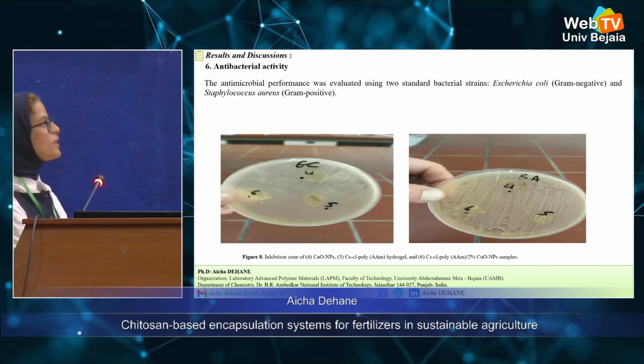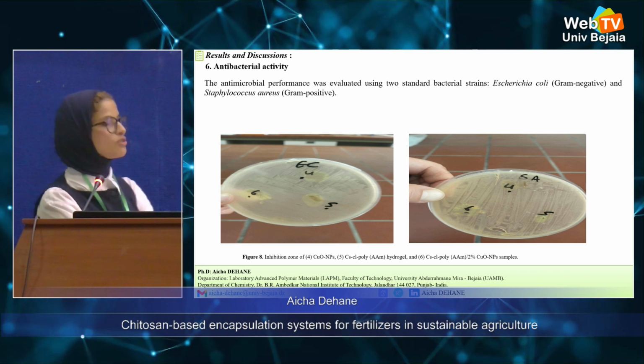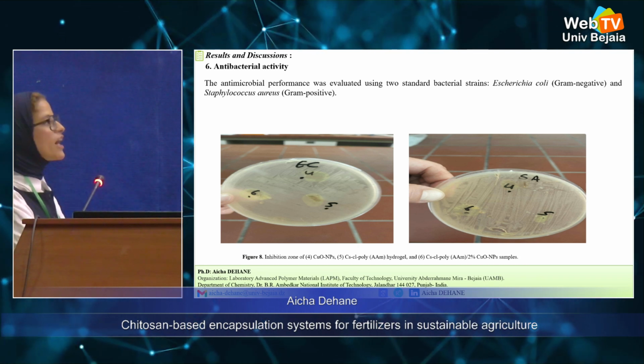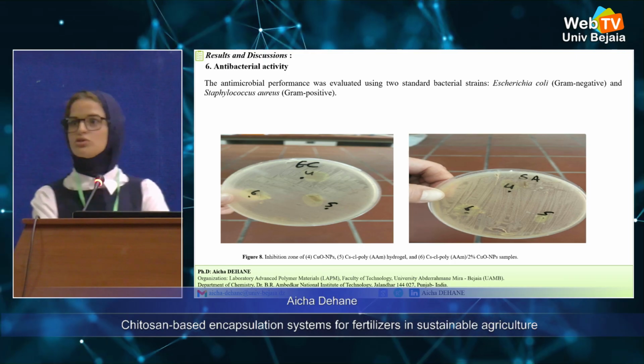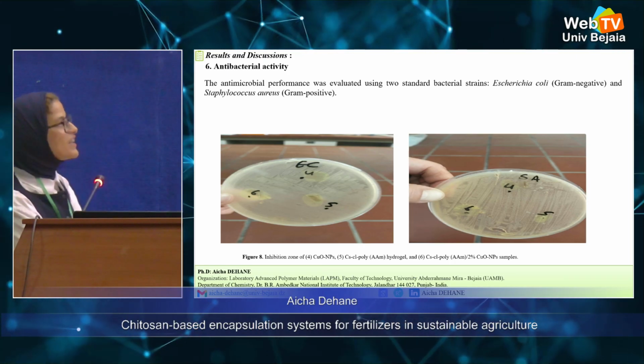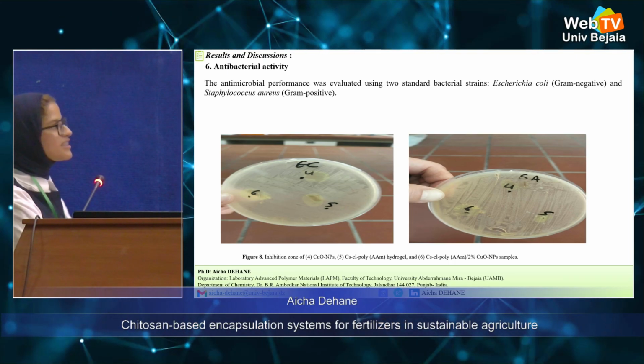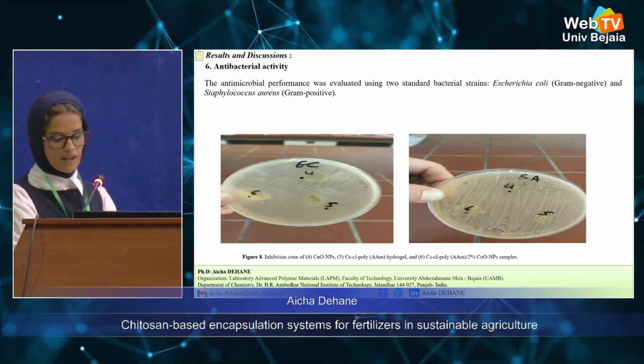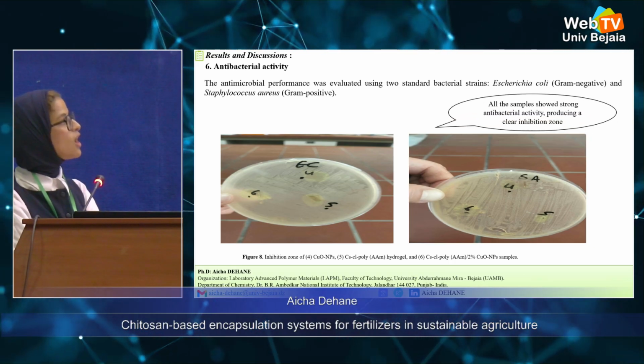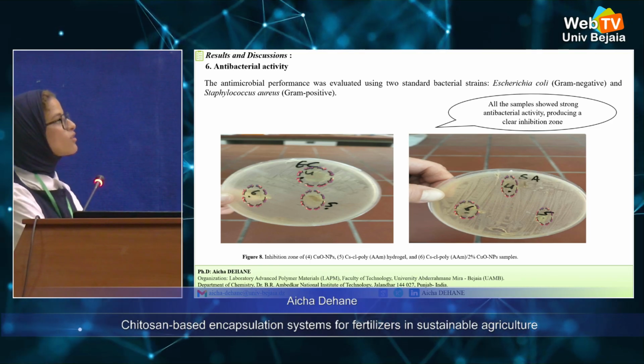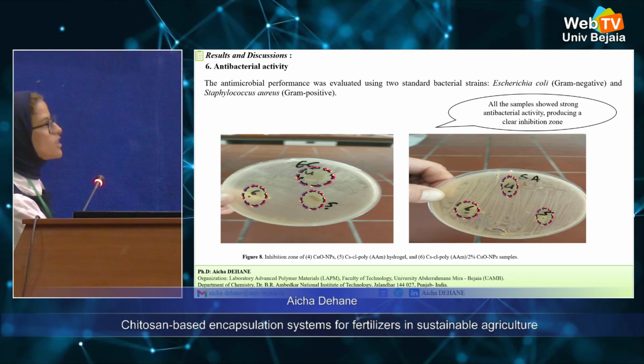The antimicrobial activity of our formulations, the hydrogel without nanoparticles and the hydrogel with nanoparticles, was evaluated using two standard bacteria, gram-positive and gram-negative. All showed strong antimicrobial activity and produced clear inhibition zones.